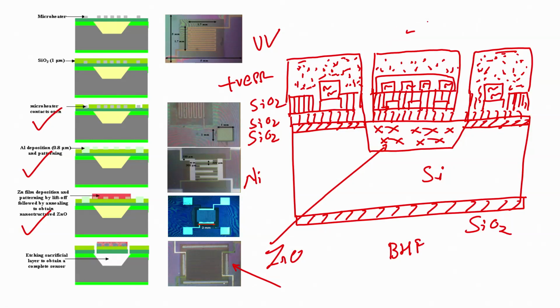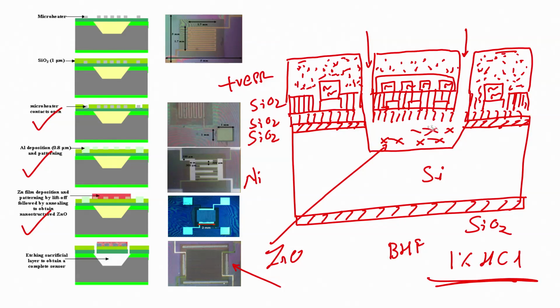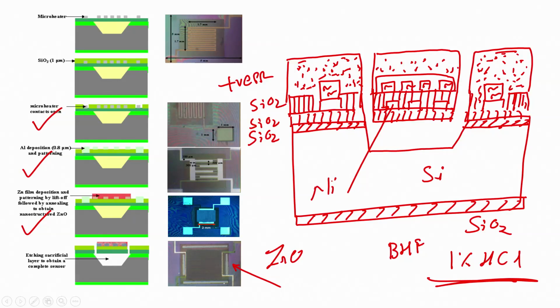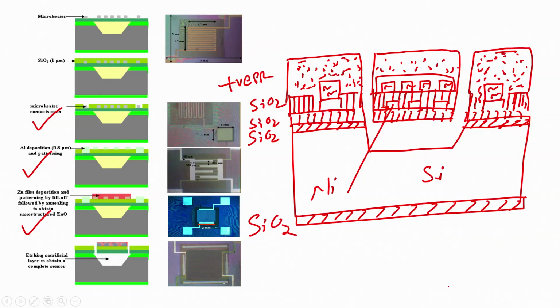So, now if I dip this wafer in 1% HCl, my positive photoresist is protecting the rest of the area, right. Here it is not protected. So, if I dip this wafer in 1% HCl, the zinc oxide will get etched, and you will be able to see a cross section image and our sensor is realized.